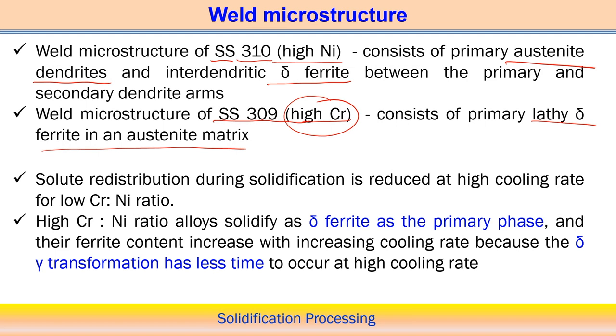Why do we get this kind of thing? Because during solidification we observe solute concentration in the liquid phase, since non-equilibrium solidification mostly occurs, and in front of the solid in the liquid phase there is usually a redistribution of the solute. When this is associated with a high cooling rate, solute redistribution occurs more in solidification at high cooling rate when the chromium to nickel ratio is low. So much more redistribution occurs, okay.